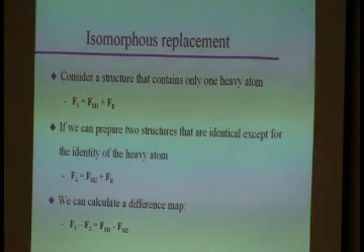So this just splits that one structure factor into two portions. One that has only the contributions of the heavy atom and one that has the contributions of everything else. And hey, these are vectors. We are allowed to take several vectors to come up with one, right? It's not a problem. After all, we could add vectors for all those individual atoms together. Oh yeah, that's what we do anyway when we calculate structure factors. So we may as well take it apart, write them separately. And right now that may not make a lot of sense, okay? But that is the starting point for it.